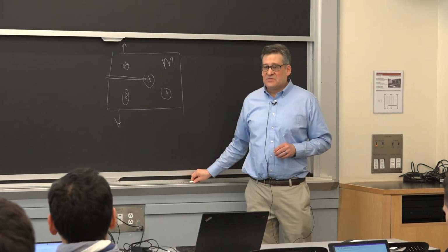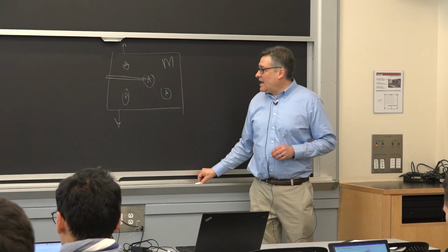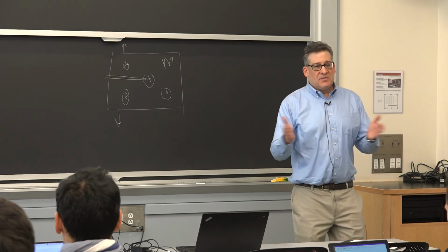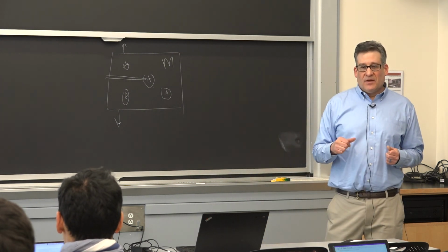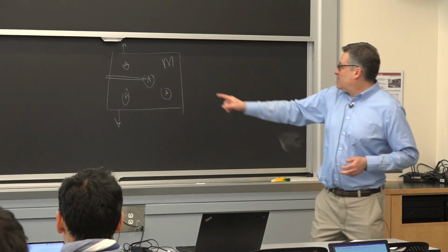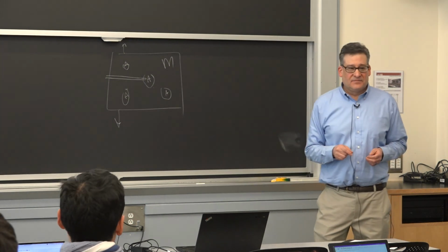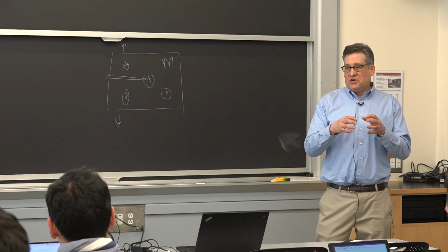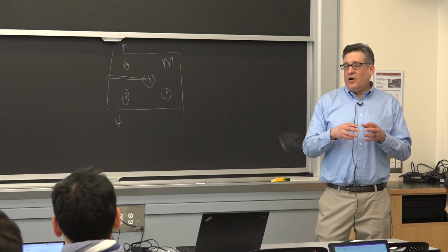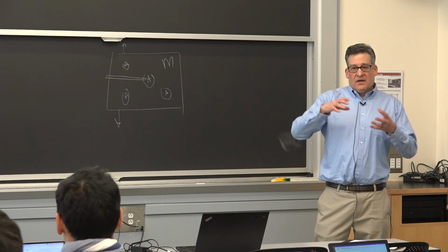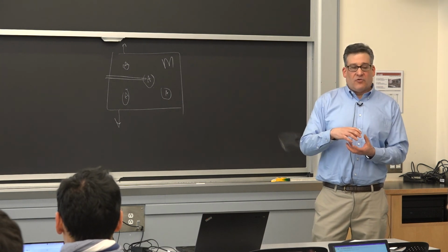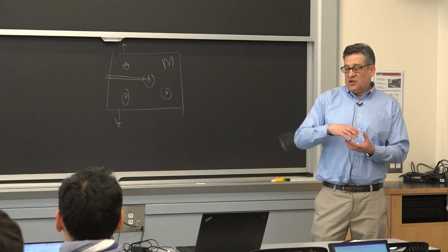However, if it propagates to the point where it hits an austenite grain or chunk of material, the energy associated with that crack opening up the material can actually transform that piece of austenite into martensite. There's a volume change associated with that, and that volume change can very effectively put a clamping load on the front of the crack, which increases toughness.